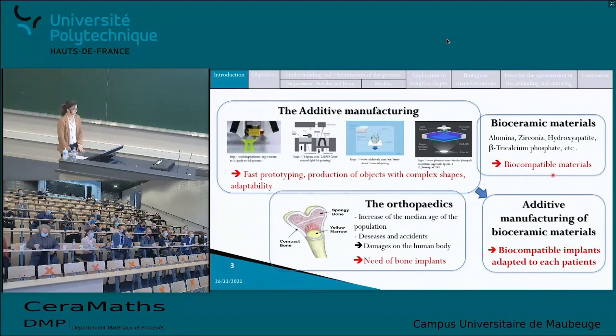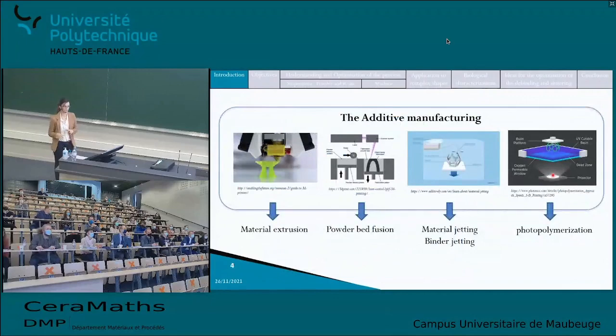So first of all, additive manufacturing can be classified into 4 main categories, depending on the type of process and depending on how the layers are built. So there is material extrusion, where the material goes through a nozzle; powder bed fusion, where there is a powder bed and the powder is sintered or melted with an energy source; material jetting or binder jetting, where the binder is jetted on the material; and finally the photopolymerization technique, where light is at the center of this additive manufacturing technique. And within the photopolymerization techniques, the stereolithography process provides a high resolution and a very smooth surface finish.